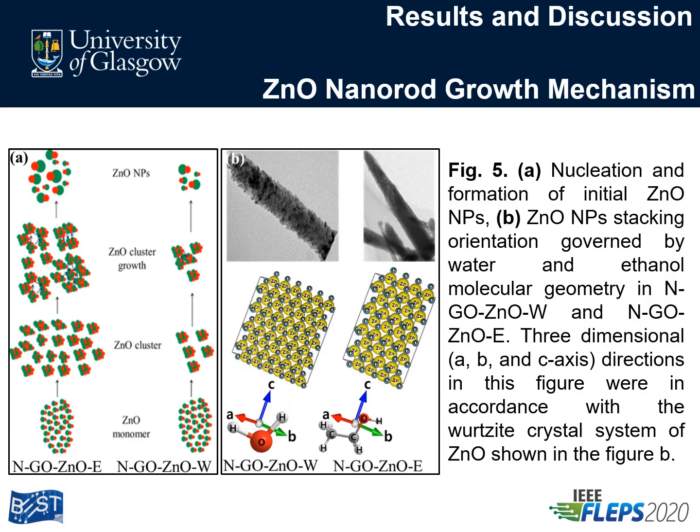M-plane interactions on another side of ethanol are stopped due to the attachment of C2H5 at the end of the molecule. C2H5 is acting as a dead end to advance the interactions along M-plane, which resulted in the formation of zinc oxide nanorods with a high aspect ratio.